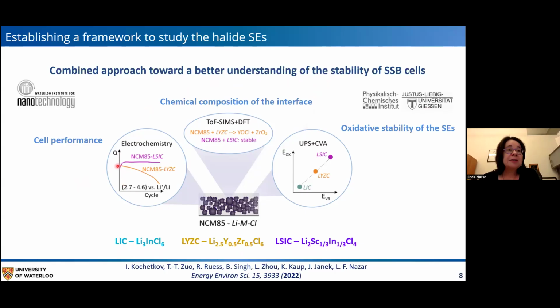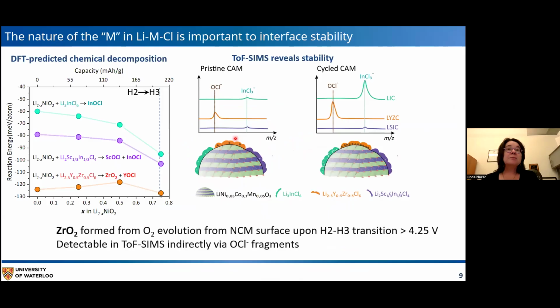And you can see here on the left that, and we abbreviate these, this one is called LISIC because it's easier to say. So you can see that this has very stable cycling, the one I just showed you, whereas the lithium yttrium zirconium chloride really behaves rather poorly. And so Jürgen's group carried out TOF-SIMS, we carried out DFT, we did all sorts of ultraviolet spectroscopy. We basically did a lot of different measurements, let's just say. And we were able to understand why the LISIC is stable, whereas the LYZC is not. And that is summarized on this slide.